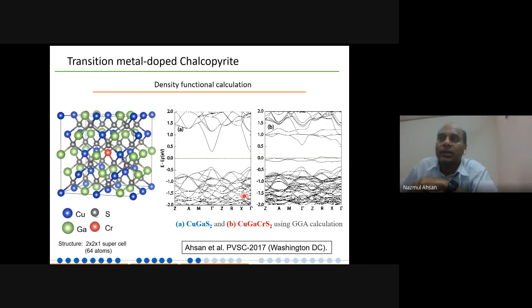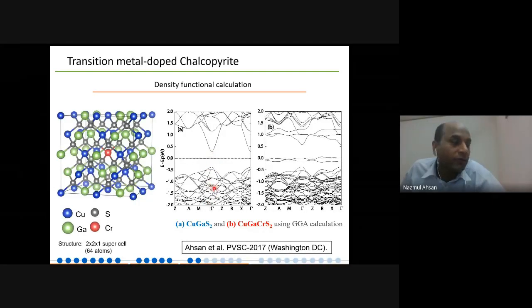Okay, let me work on this. This is a DFT calculation, a first principle calculation. DFT means density functional theory calculation. And in this DFT calculation for copper gallium sulfur, if you draw the dispersion of the electron, we see that there is a band gap. And this is the band gap, and this is a semiconductor. If the band gap edges are at the same location, we call it a direct band gap material. So this is good news.